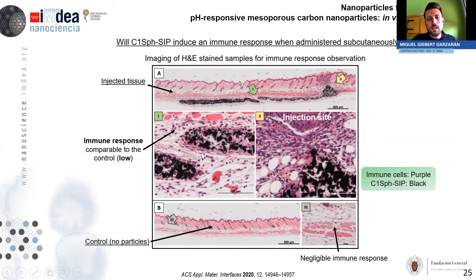If we do a crop, it is clear that in the injection site, there are many immune cells, which is logical, because it's a needle. That's the response of the organism against that. However, if we look at the nanoparticles, we can see that the immune response, which is there, of course, is quite low, and it's comparable to the case of an animal that didn't receive any injection. So we can conclude that our nanoparticles are biocompatible.